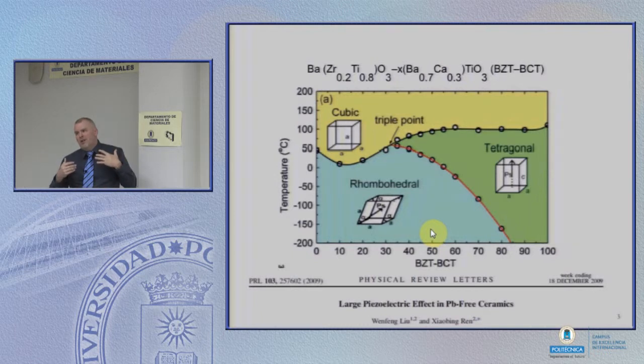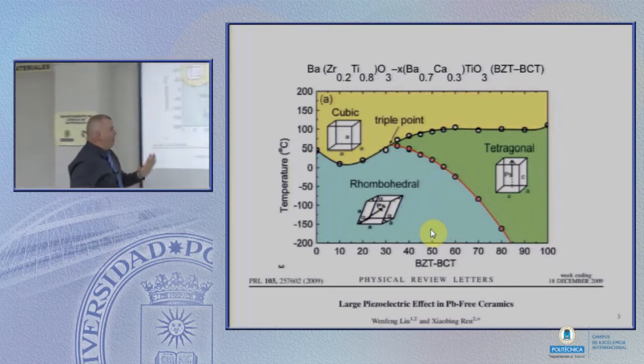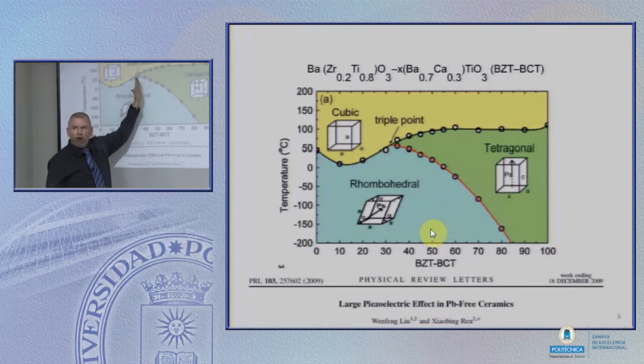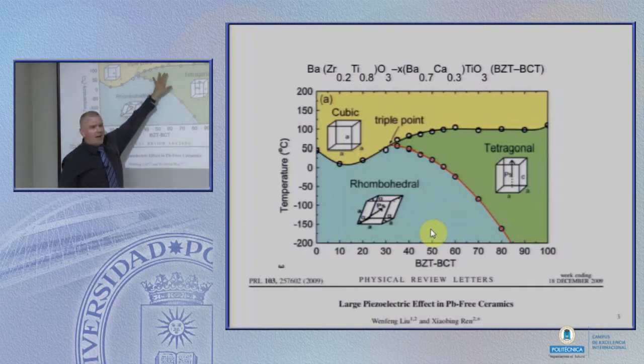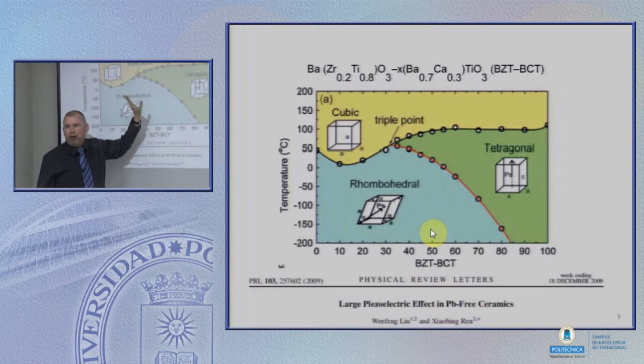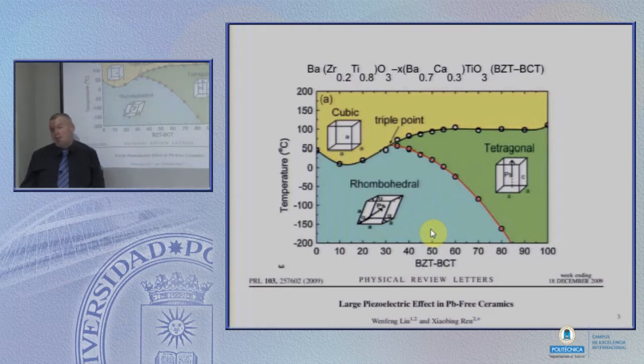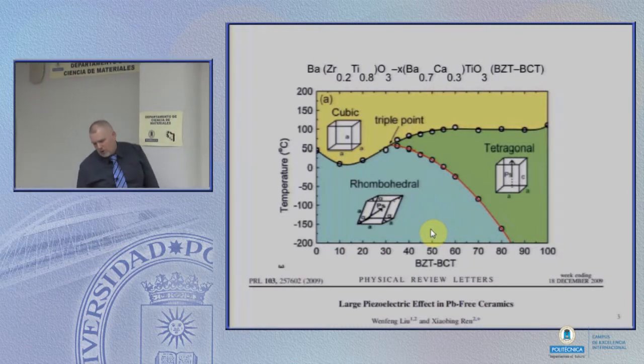My interest is trying to understand how domain motion affects these properties. And so for this system, compared to many of the more engineeringly significant materials, the beauty of this system is I can actually go with a composition here and I can cross this boundary by changing temperature, right? And so I can do it because it's sloped enough. That actually makes it not a great material for applications, but for exploration, it makes it a pretty useful material to try and understand.